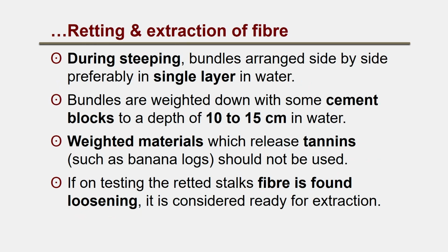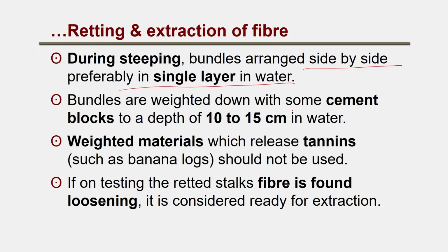So, during steeping, bundles are arranged side by side, preferably in a single layer in water. Try to avoid making stacks of bundles. Single layer is better. Bundles are weighted down with some cement blocks to a depth of 10 to 15 centimeter in water. You will require some weight so that bundles can be submerged into the water.